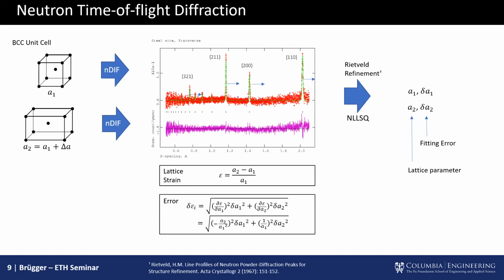But you cannot wrap, I mean, don't you need the specimen to go inside this truck, right? No, technically you could. The beauty of imaging sensors, unlike diffraction sensors, which have to be at certain angles off the sample and perfectly aligned, is that an imaging sensor looks like this box. It's just big and expensive, but you can literally just take your sample. If this is my neutron cannon, I could just move the neutron cannon up to my sample and then put my imaging detector behind it. And poof. But then, of course, the sample is radioactive, so that's the downside. I see. Interesting concept.